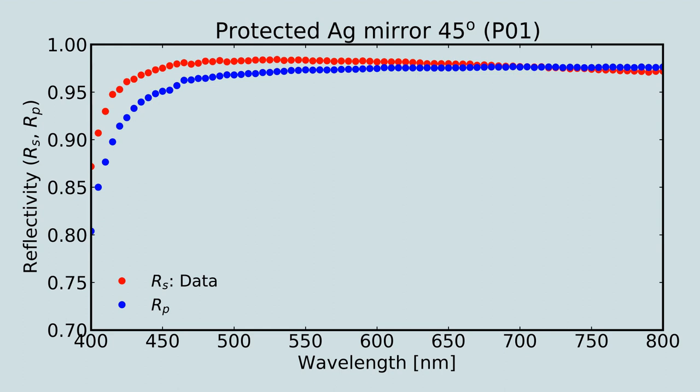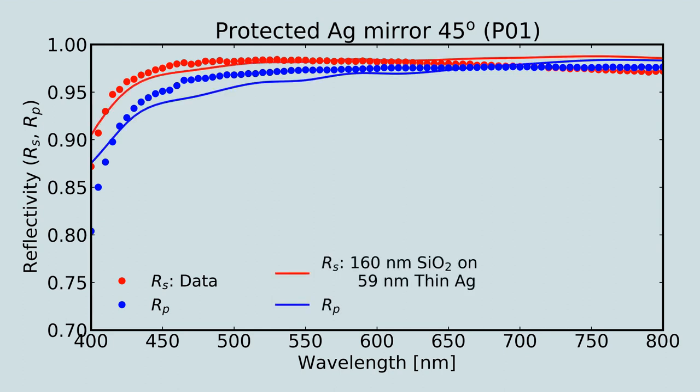Our data show high efficiency across the bandpass and are well represented by a 160 nm coating of silicon dioxide on 60 nm of silver. The data are also in reasonable agreement with the representative mirror reflectivity provided by the manufacturer.